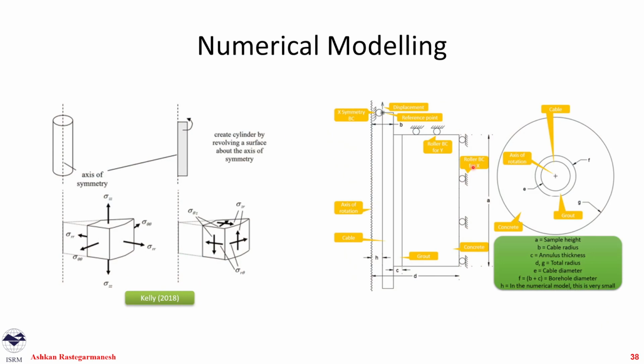Numerical modeling: we wanted to do numerical modeling, so we used the data of our experiments to calibrate a model. We decided to do a 2D model, and for 2D, we realized axisymmetry is better. But the problem with that was that you cannot model cables as axisymmetric because they have out-of-plane rotation. So we had to compromise and basically model the cable in 3D, take a cross-section of that, and assume that the cross-section is constant during the revolution that happens in axisymmetry.